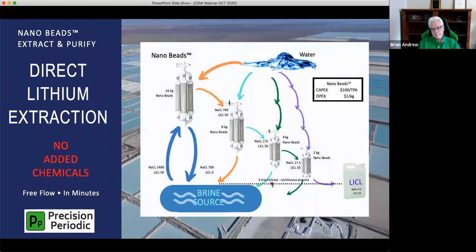We also do lithium. This one is a cascade approach where you have a filter that likes the lithium. So the lithium is attracted to the filter more than the salt or the calcium chlorides are. And so the end result is you end up with a filter that absorbs the lithium chloride and the salt and the calcium chloride, but the lithium chloride overpowers the salt and the calcium. So you always catch all the lithium and then you cascade that down the chain where you keep dropping the sodium chloride and the calcium chloride until you have no more left and you're just left with the lithium chloride. So this approach is a little bit different than the examples I gave earlier. And the end result is you end up with a very low energy, very effective direct lithium extraction without having to add any chemicals.